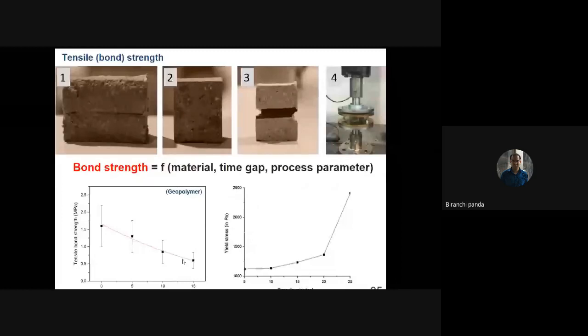But what is again a more interesting point here, it also depends upon the material. If you are using a rapid hardening material, even a 10-second delay will create a very poor bond strength. But if you are using a material having some 10-20 minutes setting time, a small delay of time gap can still provide you average tensile bond strength. So again here, the time gap is related to the material and process parameter.